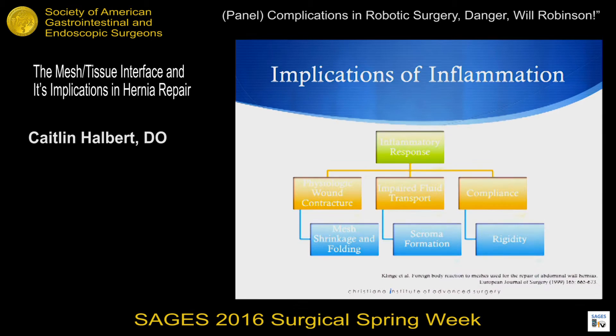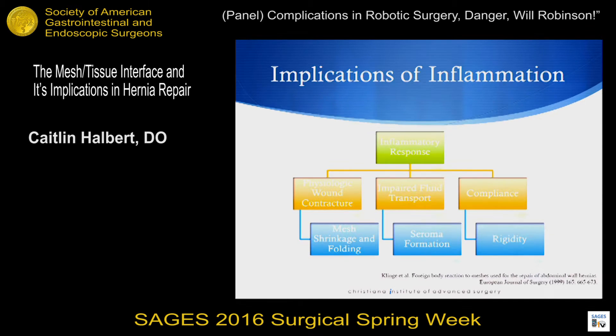The inflammatory response affects tissue integration. We're going to have some wound contracture that's natural with any inflammatory response, but what we want to do is limit that, because that really dictates the mesh shrinkage and can cause folding. Folding can injure the bowel and cause a lot of havoc in the intra-abdominal space. The solid scar plate we want to reduce as much as possible, because that impairs fluid transportation across that area, and you can certainly see seroma formation as a consequence. Finally, compliance and how that goes hand-in-hand with rigidity — you don't want a solid, rock-hard piece of mesh sitting in there.